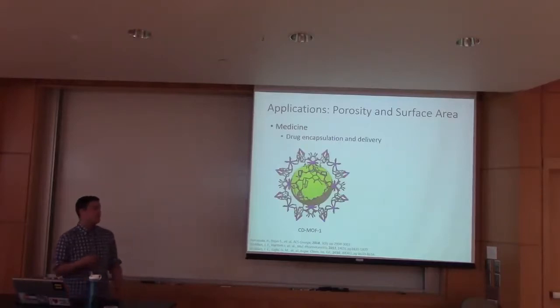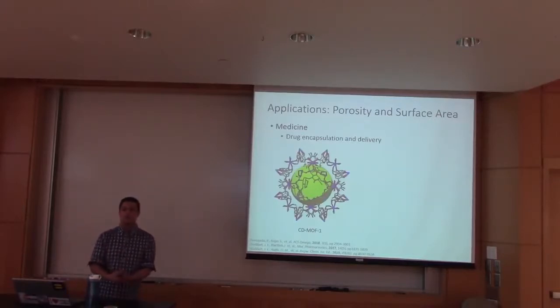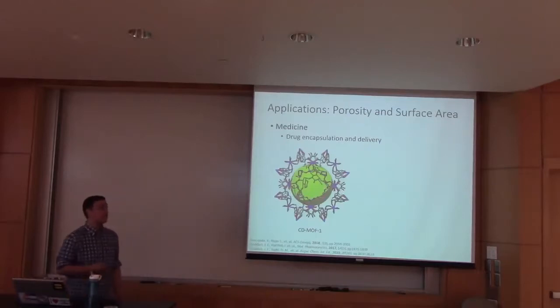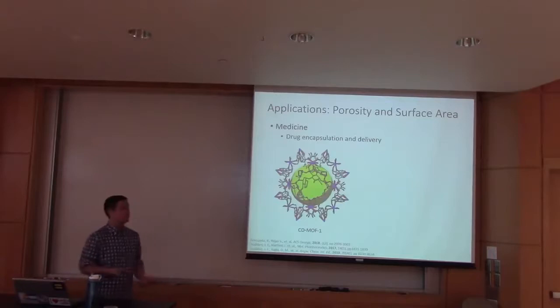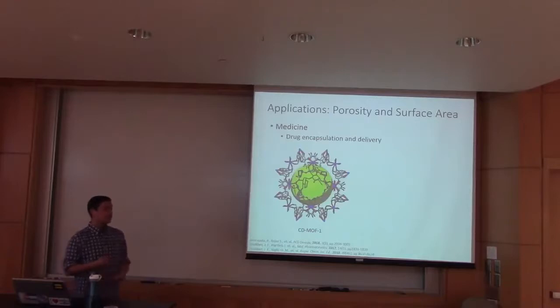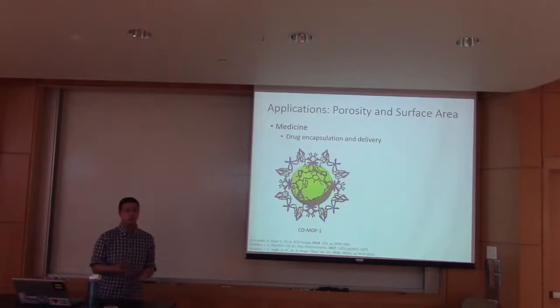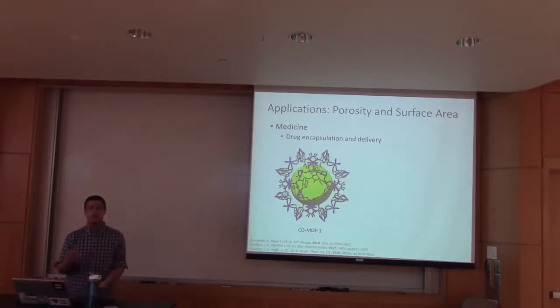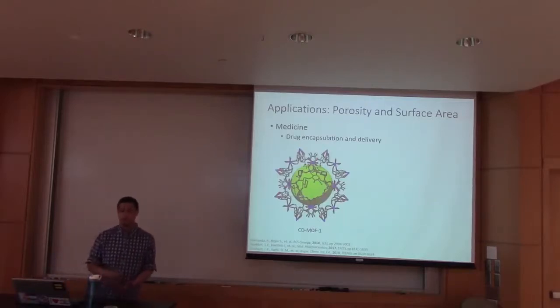And they did multiple different syntheses of this MOF. And then from that step, they were like, well, let's see if we can incorporate drugs into it. So they incorporated ibuprofen, which most, if not anybody, has heard of, or used, probably. And so it has a wide application. And what they found is that when they incorporated it into it, and they tested it on cells to do an in vitro study, they found that up to about 100 micromolar, there was no effect on cell viability, no toxicity whatsoever. So then from this step, they went on and they did in vivo studies with mice.